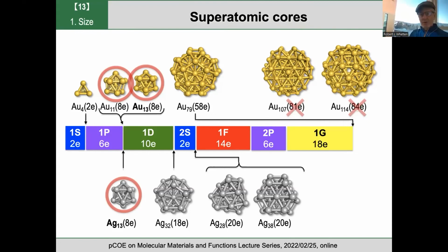In the case of the gold 144, which is labeled gold 114 for the core, we showed in some earlier theoretical modeling work that if one assumes a negative charge, -6 or -8, quite a nice large gap opens up. And so we don't know experimentally for certain whether under the strongly reducing conditions in which the clusters are normally synthesized, such strongly negative, highly reduced forms are not the dominant form. The voltammetry on the final products shows that it's quite easy to change the charge state over a wide range. Of course, when they're highly negative, they're very reactive. They're very good electron donors, so one doesn't expect them.